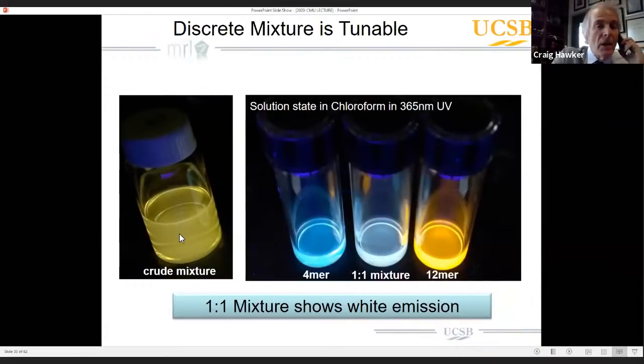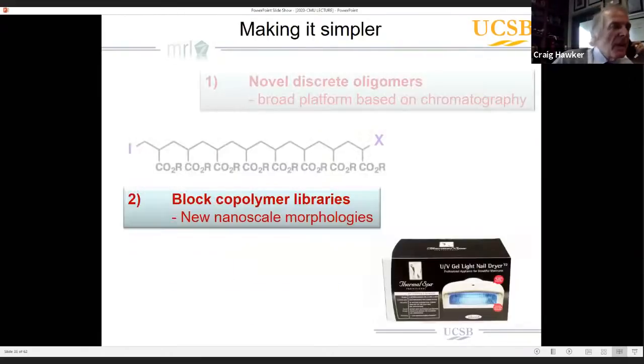And so in this case, you can see the color of the crude mixture, the color of the tetramer and of the 12mer. And the interesting thing is that when we do a 1:1 mixture of the tetramer and the dodecamer, we actually get a mixture with an average degree of polymerization of 8, the same as the crude mixture. But because we've really controlled the length of what constitutes that mixture, we now get white emission. And for many of these light emitting applications, you really need white emission if you're going to be able to commercialize these materials. So this was a really nice demonstration that we could expand this concept of controlled radical polymerization and automated chromatography to a wide degree of backbones and also a wide degree of applications.